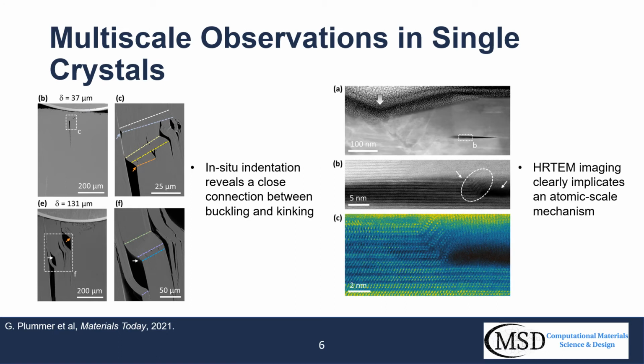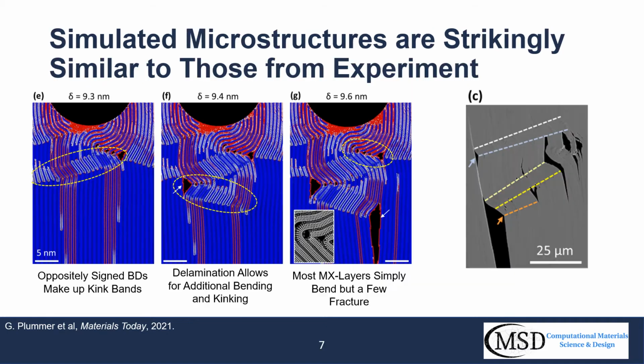Secondly, here are atomic scale high-resolution TEM images of a MAX phase after being indented, and they reveal a delamination crack beneath the indenter and, strikingly, a kink band that is only 3 unit cells thick. This provides clear evidence that kinking is governed by atomic scale mechanisms.